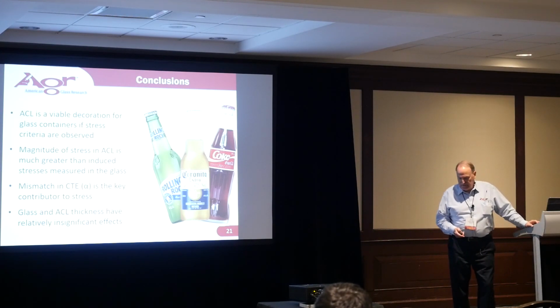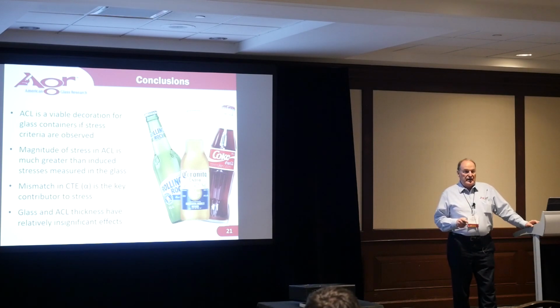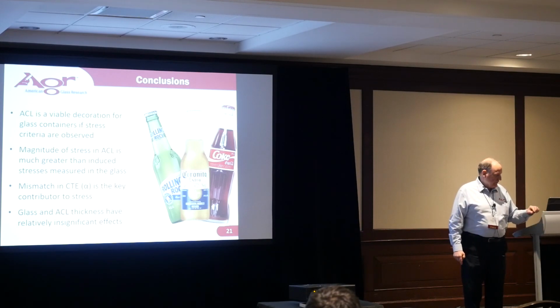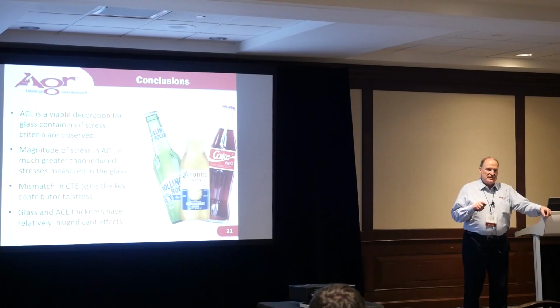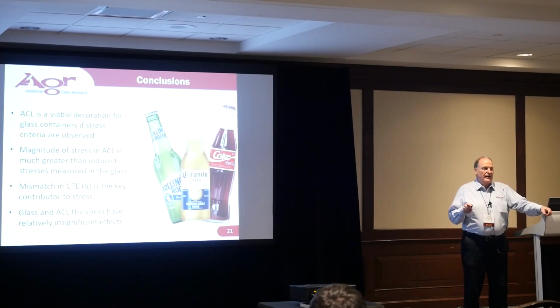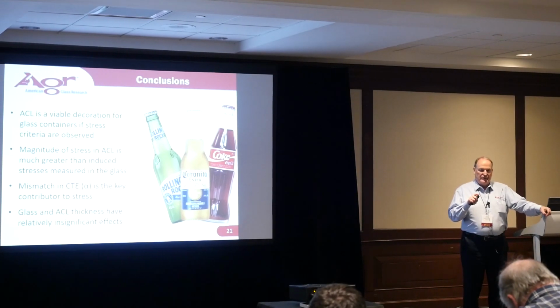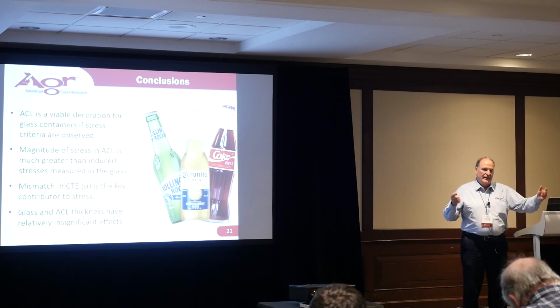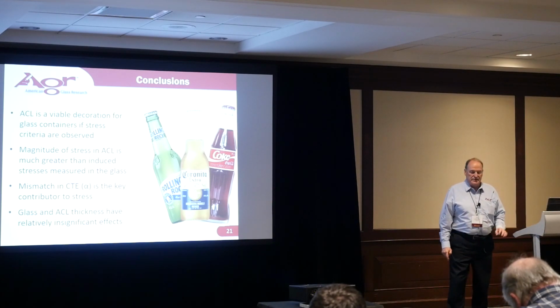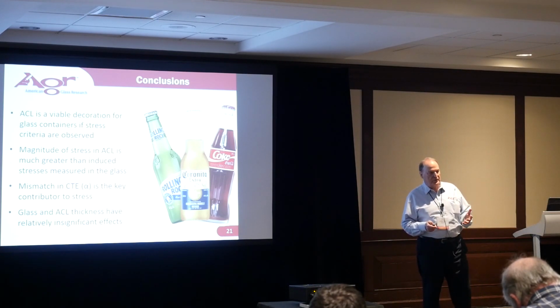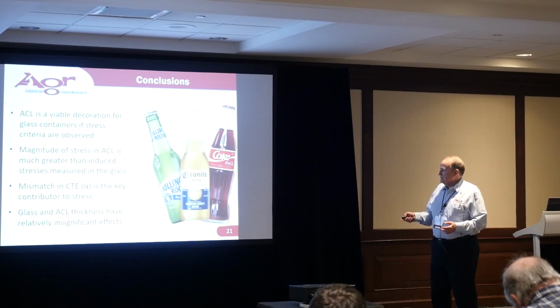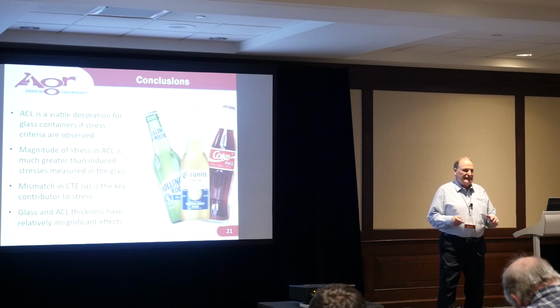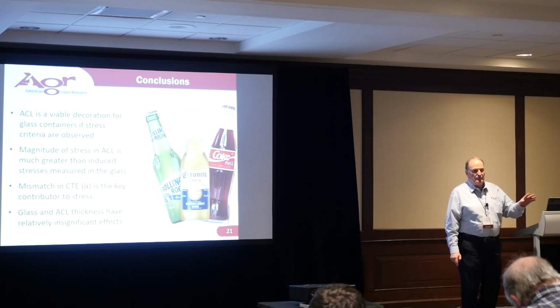Well, after a little more examination, the coefficient of expansion of the ACL was the one that was constant. And with a little bit of further investigation, we found that the glass supplier was starting to use more cullet. And the cullet was throwing off his composition. And what used to be a coefficient of expansion of the glass that was higher than the ACL, through the use of cullet, became lower than the ACL. He ended up with serious problems with cracking in the ACL. So the main issue here is the coefficient of thermal expansion. The glass thickness and the ACL thickness, yeah, there's a slight problem there, but minimal, not to worry about.